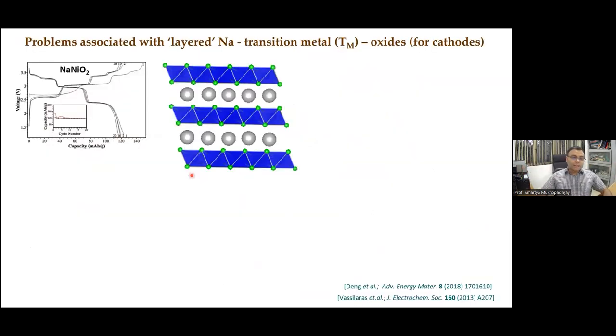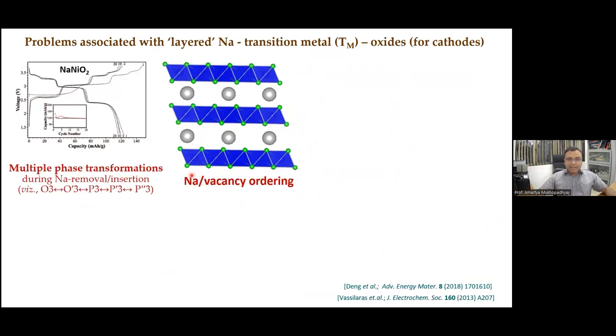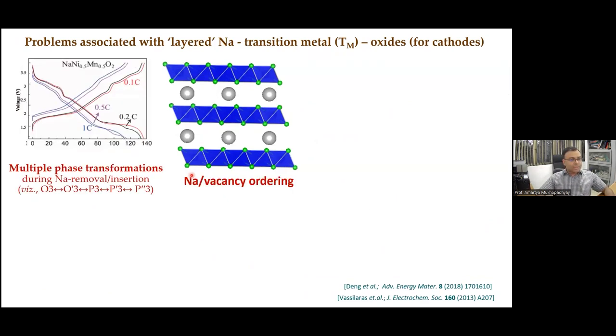So in a nutshell, again, as a summary, these are the problems associated with the layered transition metal oxide, the layered sodium transition metal oxide. So during desodiation, that is charge discharge, they undergo multiple phase transformations. And so that leads to a structural damage and loss in capacity, that is capacity fade.